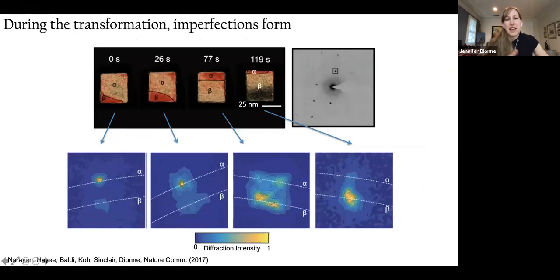So I mentioned that we have intercalation beginning at the corners, subsurface wetting. Eventually, the hydrogen-rich phase stabilizes along a particular direction, so that way it can propagate along the nanoparticle. And when we have alpha-beta phase coexistence, we're going to have quite a bit of strain within the nanoparticle due to that 3 or 3.5% lattice mismatch between the alpha and beta phases. And during the transformation, we can look at diffraction of individual nanoparticles. So here I'm showing you diffraction of an individual nanocube.